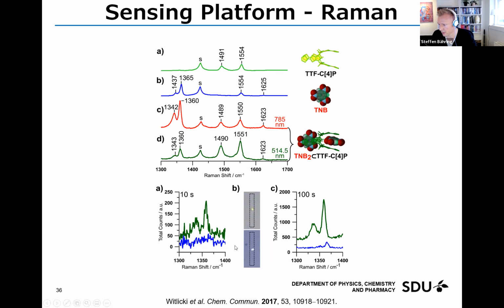One final experiment that we did was to do it on solid material. So we have the pristine calix[4]pyrrole. We have the crystalline trinitrobenzene, and then we have the complexation with calix[4]pyrrole. And you can see here that at only 10 seconds we have a signal for the nitro group of the complex, and at 100 seconds we have much more signal for the complexation. So just in the solid state, we are able to show that we can detect TNB much more efficiently than without the calix[4]pyrrole being present.